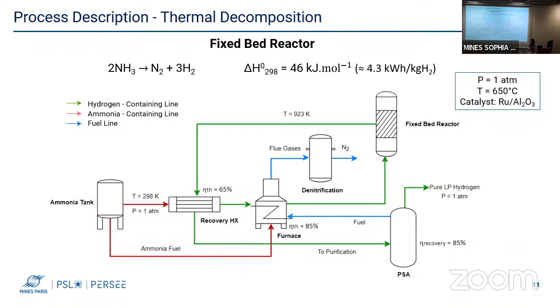Then a question on the precision of some data. Sometimes you go very precise in the numbers that you give in the manuscript. For example, on page 114, when you give a peak particle size, you go down to 2 digits after the decimal, so even below the angstrom. Is this really precise? No, this is not really precise. It's very difficult to go to 0.001 nanometer to measure it. I think it would only be enough to put one figure after the decimal. So you think we can go at plus or minus 0.1 nanometer for that measurement? I think so. Okay.